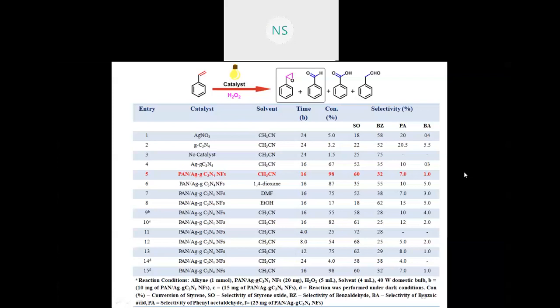And when we go for the selectivity of this particular catalyst, there is a formation of styrene oxide, benzaldehyde, benzoic acid, and different byproducts. The bracket is showing the major and the other is showing the minor. Here 60% yield is obtained, and for the others it is 32, 7, and 1%. Means the major is SO, showing 60% of that particular material. That is styrene oxide. Formation of styrene oxide is the major one here.